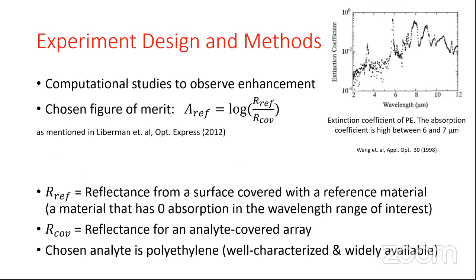So for that, I did computational studies to observe the enhancement. And by enhancement, what I mean is, compared to a structure that is, for example, a planar case, what is the signal enhancement, the absorption enhancement of the structure. And the chosen figure of merit is the logarithm of the fraction of reflectance from a surface covered with a reference material divided by reflectance for an analyte covered array.